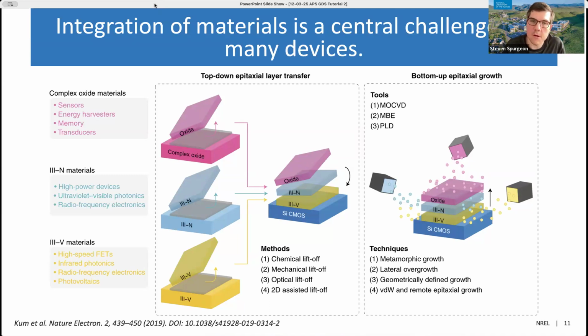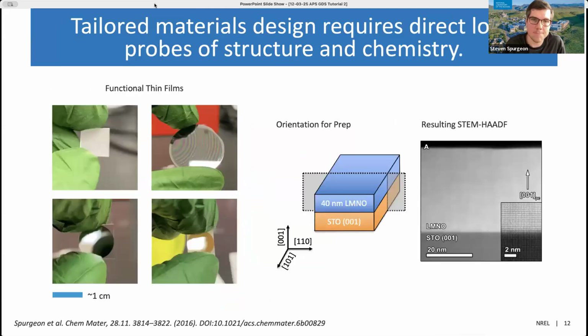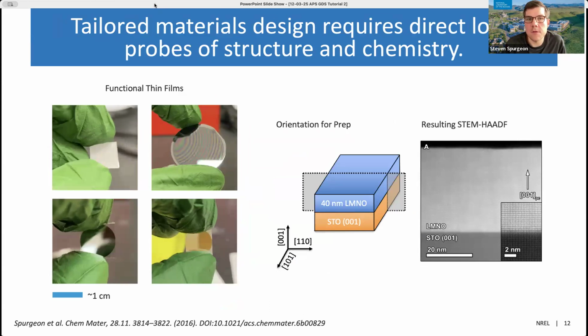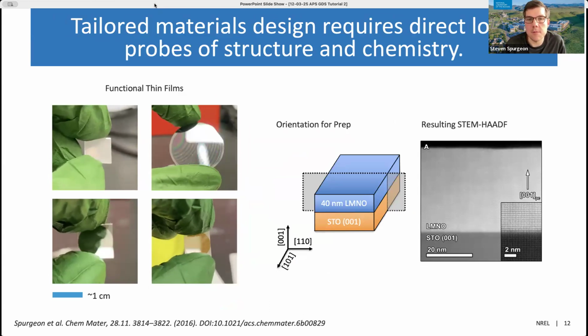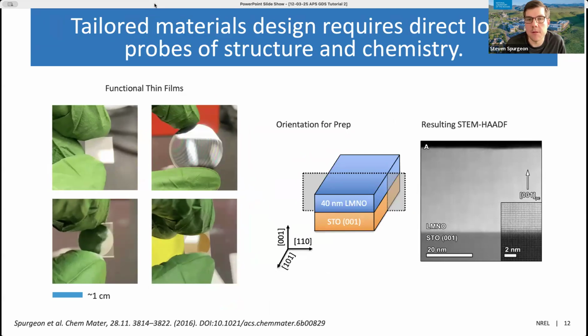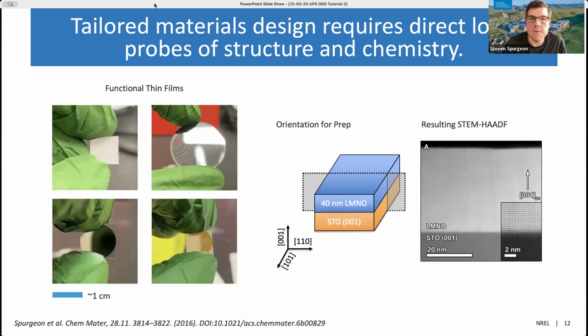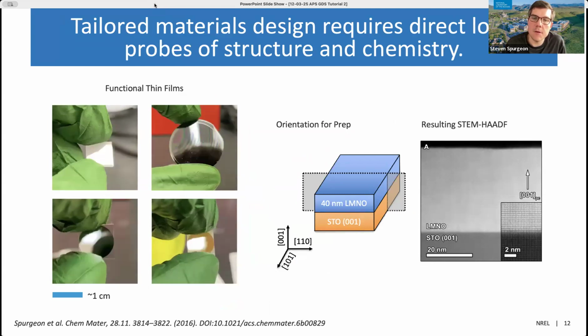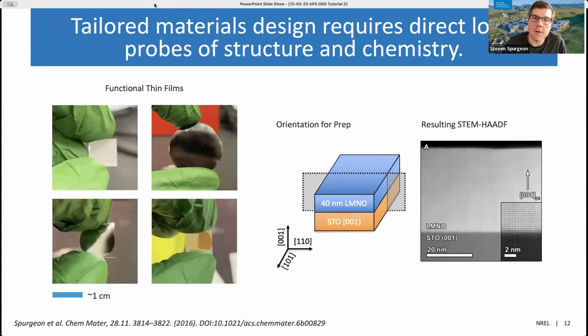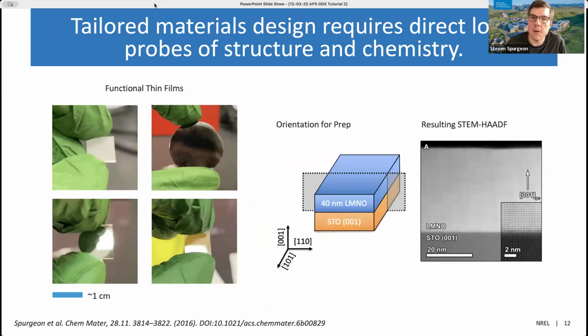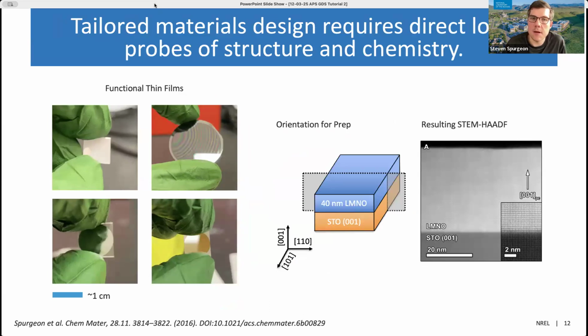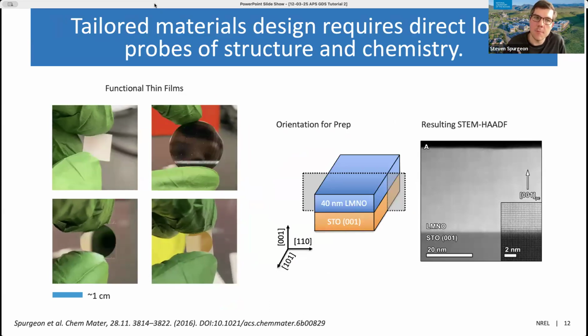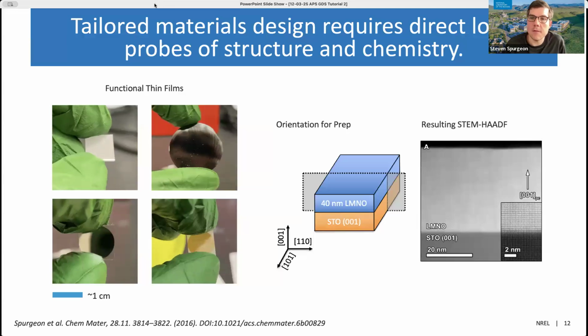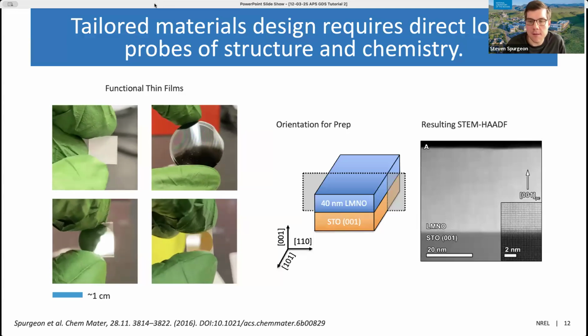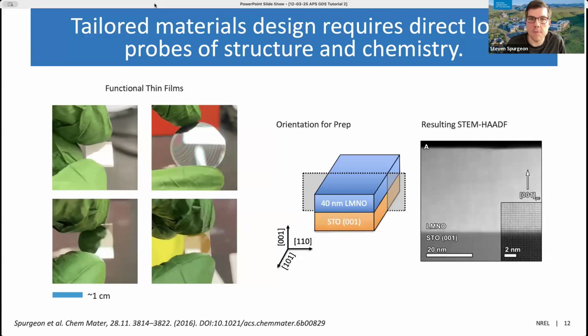Regardless, in both cases here, our goal is to understand these interfaces and what the actual resultant products are of our synthesis. So our knowledge of materials design and development of these sorts of functional systems depends on analyzing them at the most fundamental level, all the way down to the atomic scale. So on the left-hand side here, we've got examples of macro scale images of these materials. And then we can use a variety of different sample preparation techniques to cross-section and to image these materials. Conventionally now we use techniques like focused ion beam preparation to actually ion mill cross-sections into these materials. And then through careful preparation, careful imaging, we can analyze these materials' microstructures down to the atomic level.